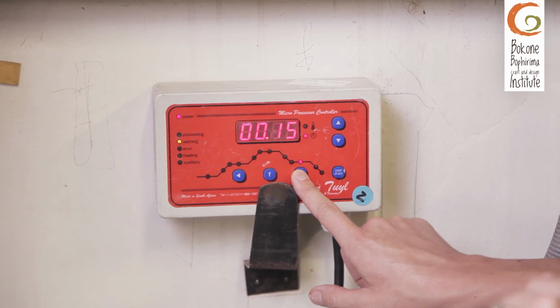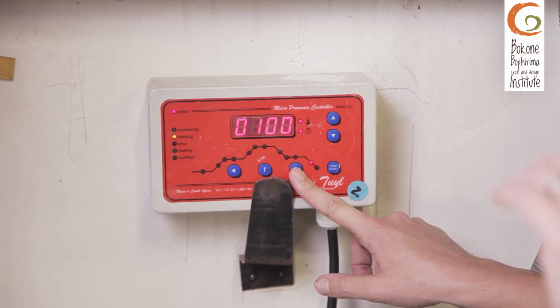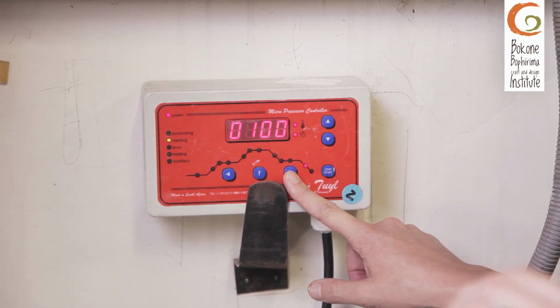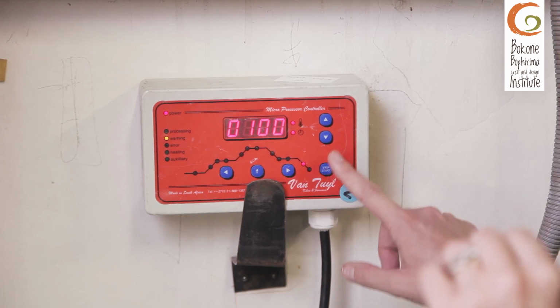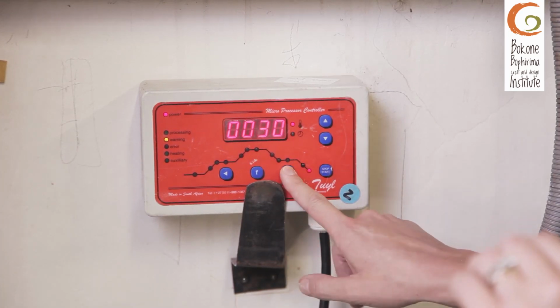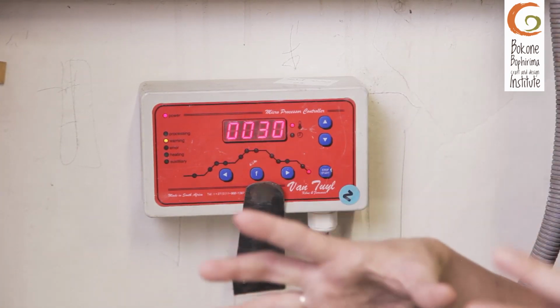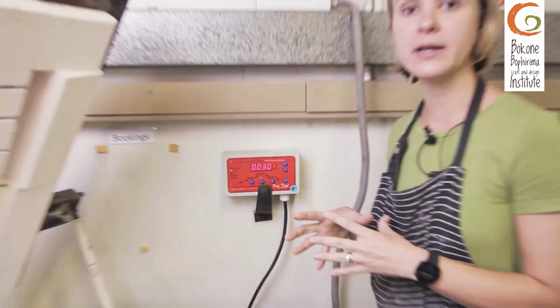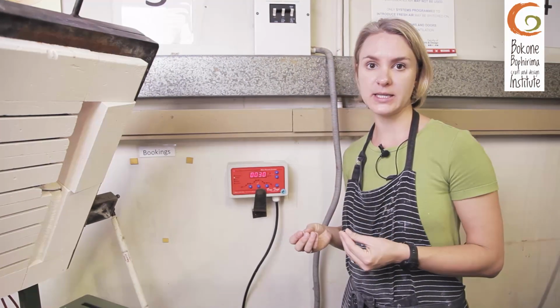Now I'm going to bring my glass down. Remember, again, the thicker the glass is, the slower this process will be. I'm only going to bring it down 100 degrees an hour to 30 degrees, and in this process, it will slowly cool down and my glass won't then be under tension anymore.